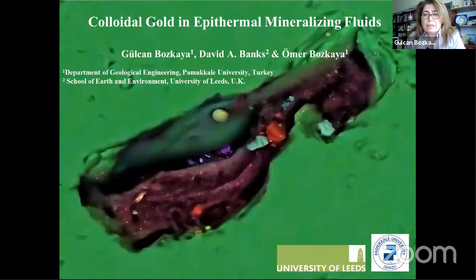When we think of transporting elements to make a deposit, it is solubility in solution we should consider. For most elements, solubility as chloride complexes is important, but gold is different, being transported primarily as bisulfide complexes. These are sensitive to change in pressure, breaking down to hydrogen bisulfide and depositing gold. The atoms aggregate, forming nanoparticles, colloids, and eventually macroscopic crystals. In our study, we present evidence that gold colloids are present in mineralizing fluids and provide concentrations greater than possible in solution.